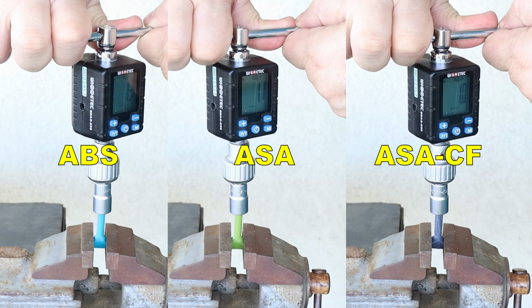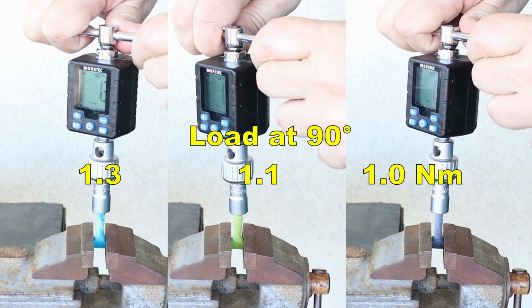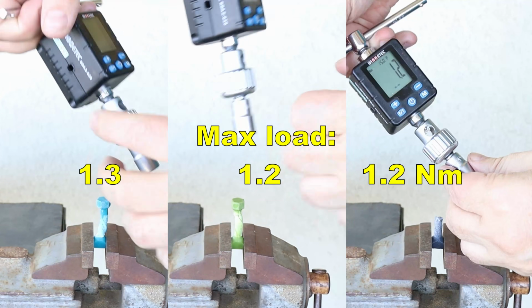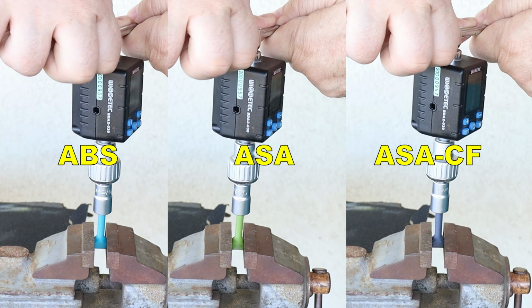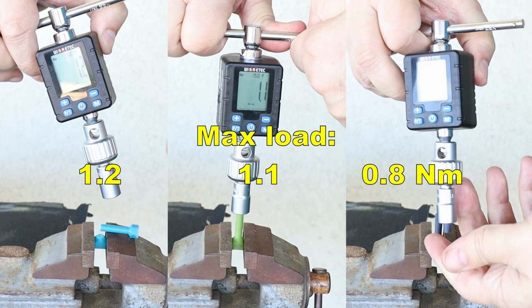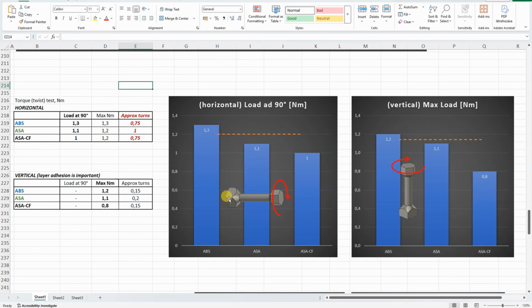Torsion test, starting with horizontally printed versions, load at 90-degree rotation, and the maximum load. Printed in vertical position, only the break load is recorded here. Printed in horizontal position, load at 90-degree rotation, the strongest is the ABS, and the other two ASAs are a little bit below this average line. Printed in vertical position, ABS and ASA are very similar, very close to that average line, and ASA-CF is noticeably weaker because of that weaker layer adhesion.